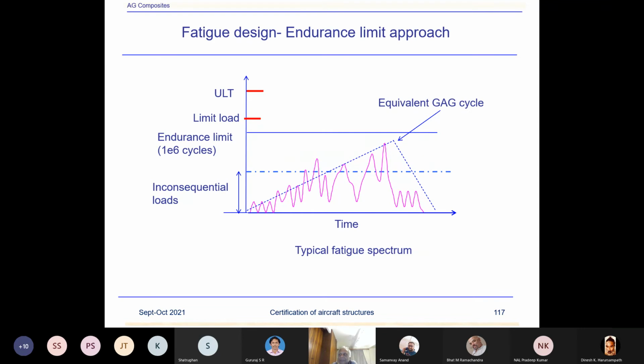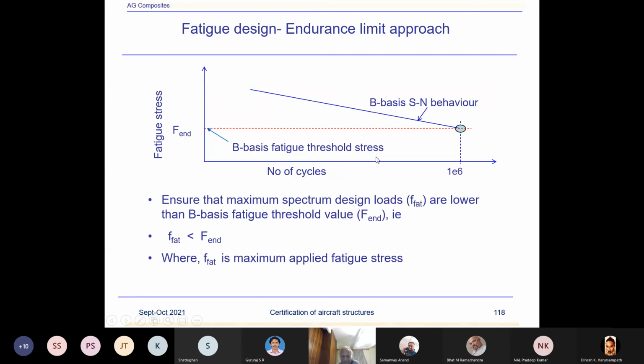You can determine the SN curve, put in your point, determine the allowable stress for 100,000 cycles and write the margin. But generally in composites, we use the endurance limit approach. So we work out what my gag cycle stress is, the maximum operational cycle basically, and the minimum. Based on that, the stress ratio will be determined. Then, using the endurance limit approach, we have the SN curve generated for a particular mode of failure. If it's a joint, for the joint; for open hole fatigue, that. And then normally we define the endurance limit as 1 million cycles.